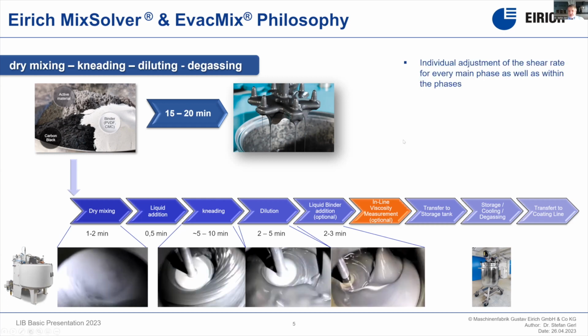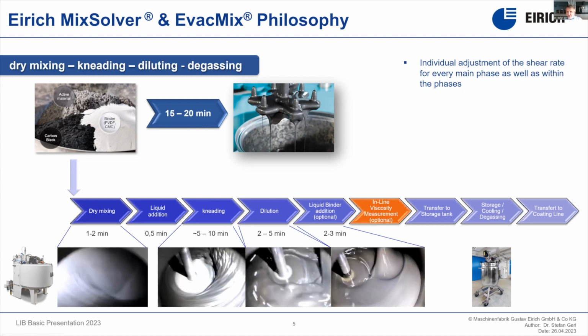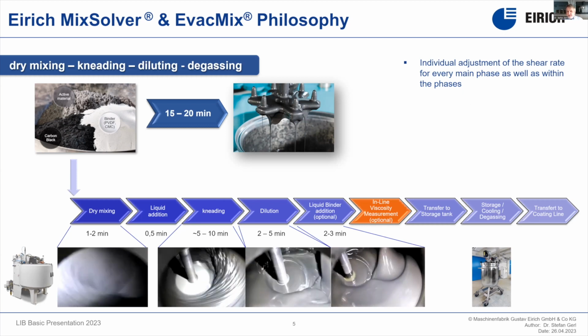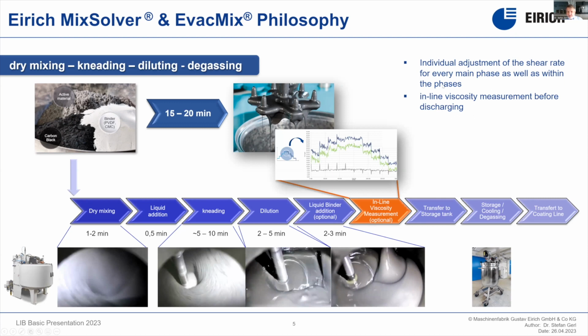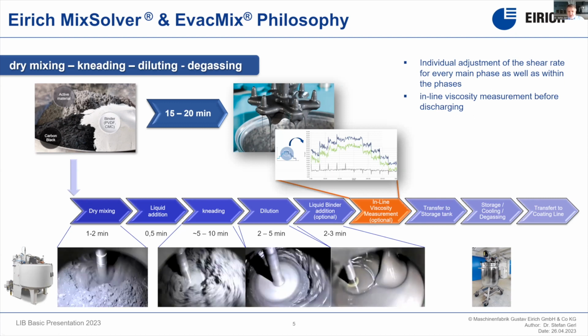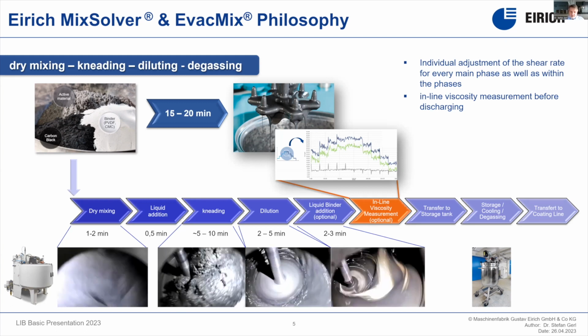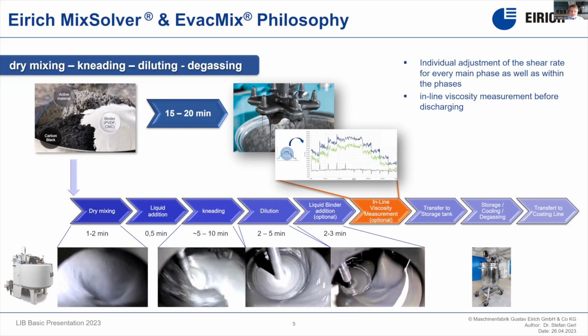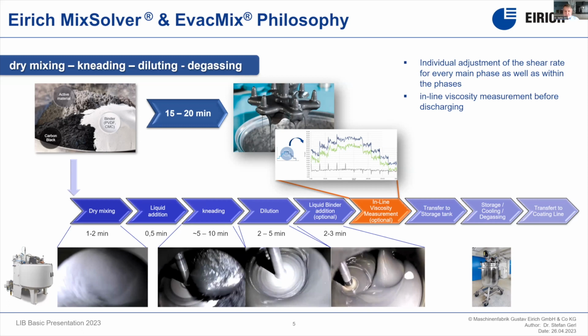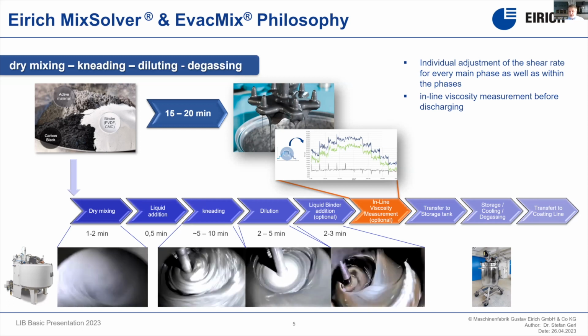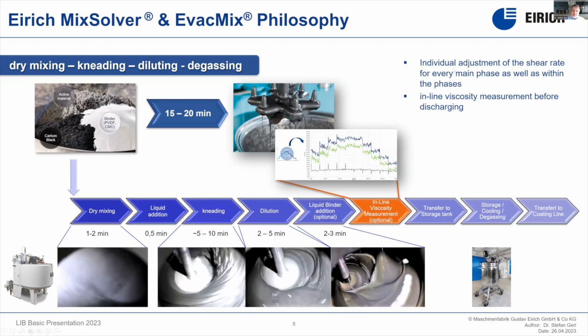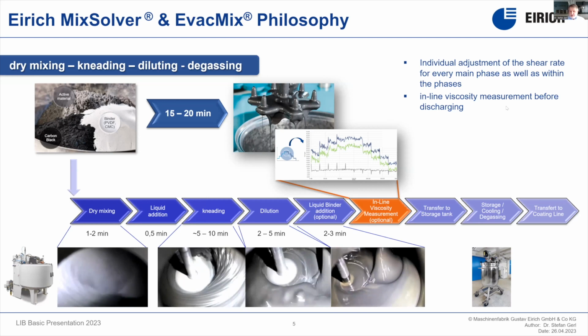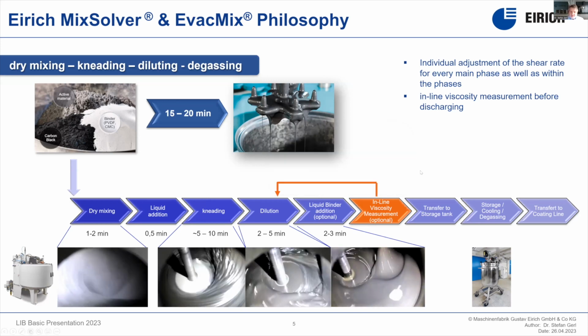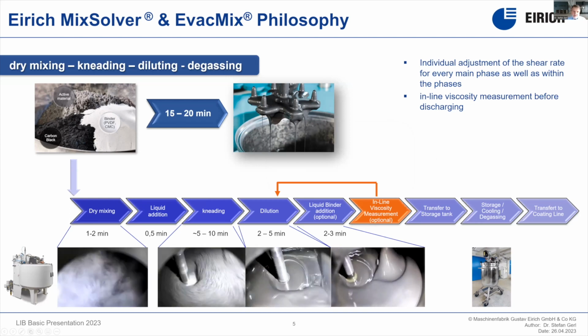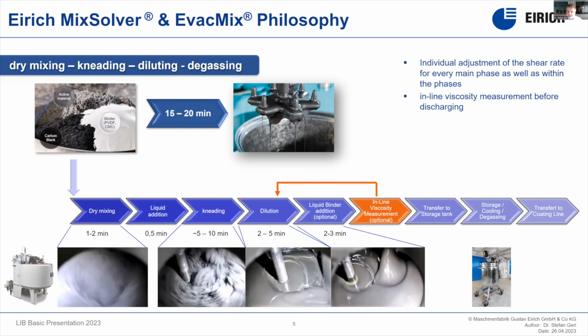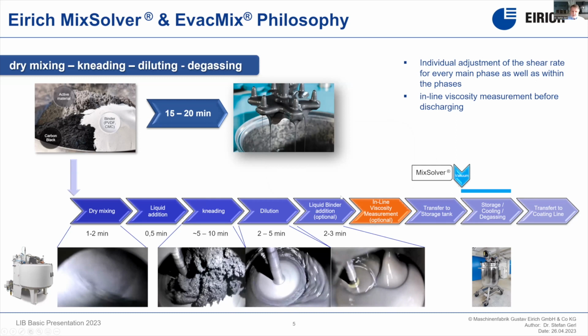The advantage of the system is that you can adjust all the parameters like time and shear rate in every phase. You can even make sub-phases within the kneading phase. We have an additional possibility to measure the viscosity, like a viscometer, inside of the machine. As our tool doesn't contact bottom or wall, we can stop, for example, the mixing chamber, start rotating the mixing tool at defined speeds, and then measure the torque, and by this we get a response like within a viscometer. This helps us to qualify the slurry before we discharge it into the downstream transfer and storage tanks. The inline viscosity measurement can be made at the end, or of course in between. It could even be repeated several times if necessary, to qualify the slurry before discharging.